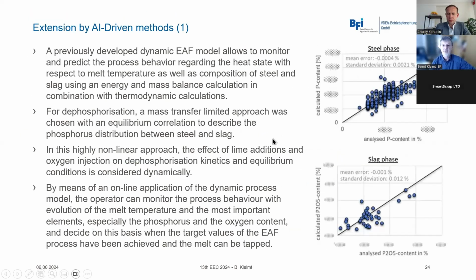So of course you can assess the phosphorus content in liquid steel by means of a dynamic process model, which we also have developed. And this model allows to monitor and predict the process behavior regarding all the important values of the heat status, like the melt temperature and the composition of steel and also of the slag. So the model uses an energy and mass balance calculation in combination with thermodynamic calculations for the elements which are reacting with oxygen and which are not so easy to determine.